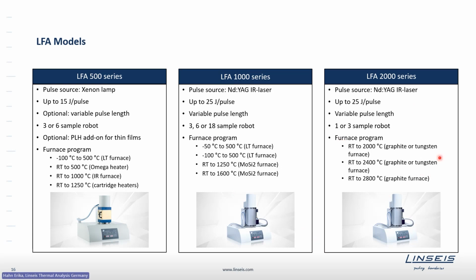And the last series is the so-called LFA 2000 series, labeling all instruments which measure up to 2000 or 2800 degrees Celsius. Here you can already see that the sample throughput is a little bit more limited. One can either measure 1 or 3 samples at the same time. What can be mentioned here as well with the high temperature series is that we also have tungsten furnaces available or graphite furnaces to cover different applications. All of these models typically measure in vacuum. The high temperature versions typically measure in helium or argon. However, all of these instruments have the possibility to perform measurements in vacuum or in different gas atmospheres with a complete temperature range each.